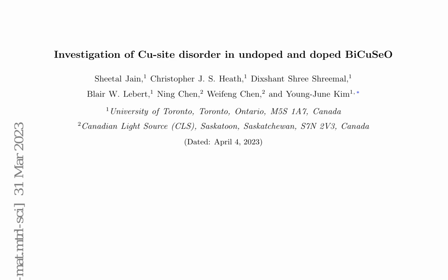reaction process. XRD measurements were performed using a Rigaku SmartLab diffractometer with Cu K alpha radiation and a nickel filter to block Cu K beta radiation. The powder samples were thoroughly ground and mounted in Bragg-Brentano reflection geometry. Heating and cooling from room temperature were done using Anton Paar DHS and DCS sample stages, respectively, under vacuum conditions.